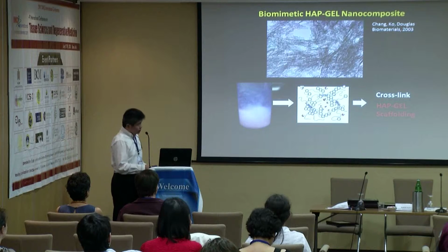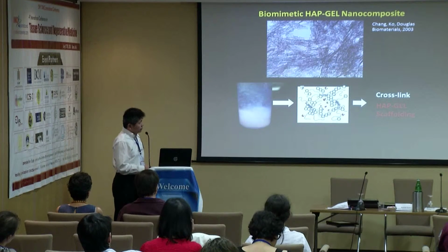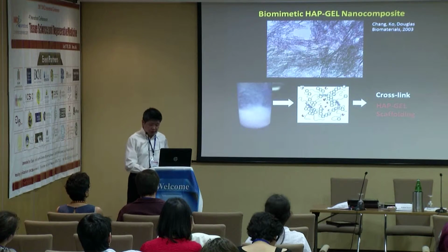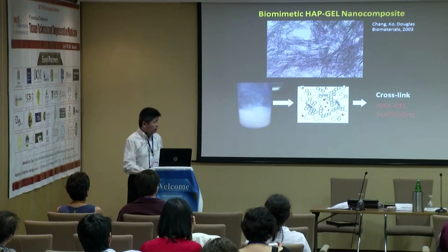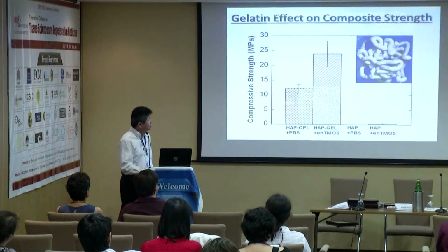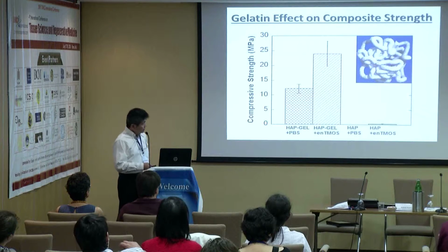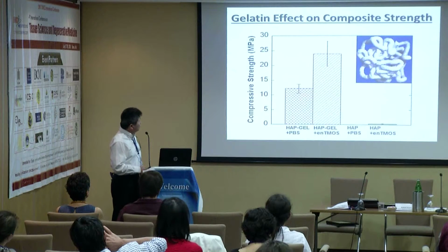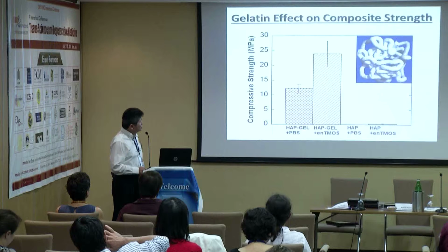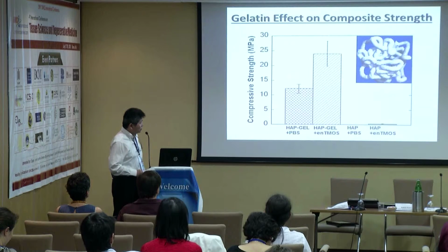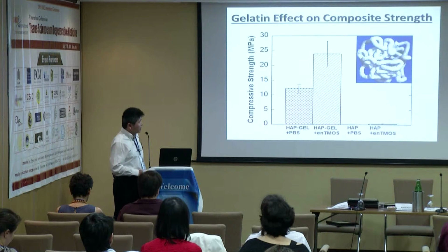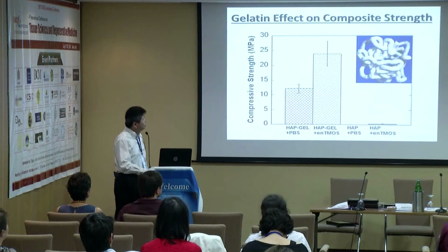During the past 10 years, our group has been focusing on making this material into the best composite material, one which has enough strength to support the defect and also a better biological response. Here we show why this material is interesting: the gelatin has an effect on the mechanical strength. Comparing the material with and without gelatin, you can see that when it forms a composite, the mechanical strength is much higher than that of pure hydroxyapatite.